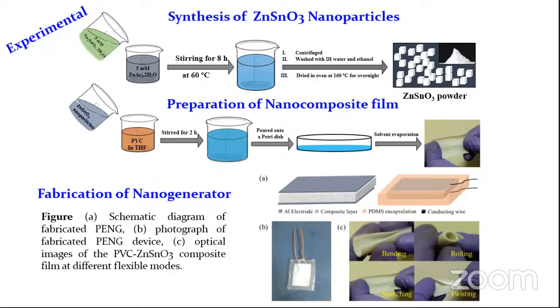This is the synthesis of zinc stannate nanoparticle. We synthesized the zinc stannate nanoparticle simply by mixing an equimolar solution of sodium stannate and zinc acetate, stirring at 60 degrees centigrade for 8 hours. After completion of 8 hours, we centrifuged and washed several times with DI water and ethanol, then dried it in an oven at 160 degrees centigrade overnight. After preparation of the zinc stannate nanoparticle, we mixed the nanoparticle with PVC in THF solution, which on solvent evaporation gives a film.